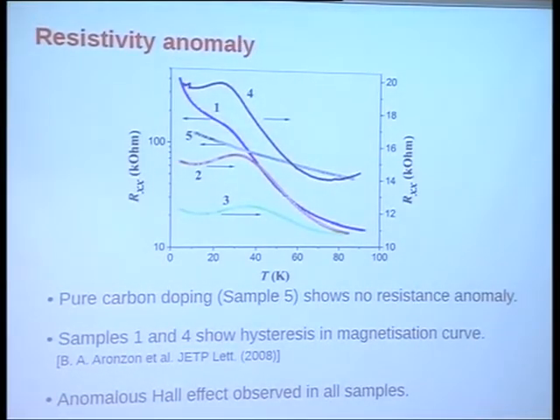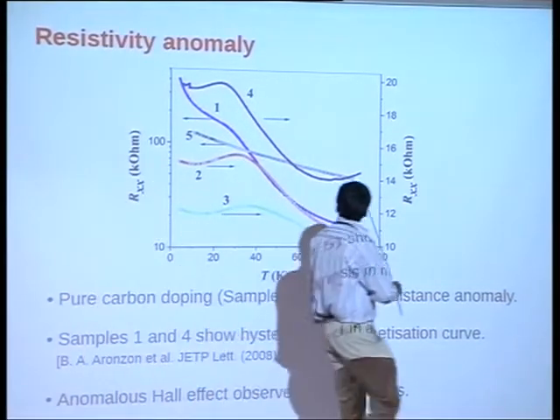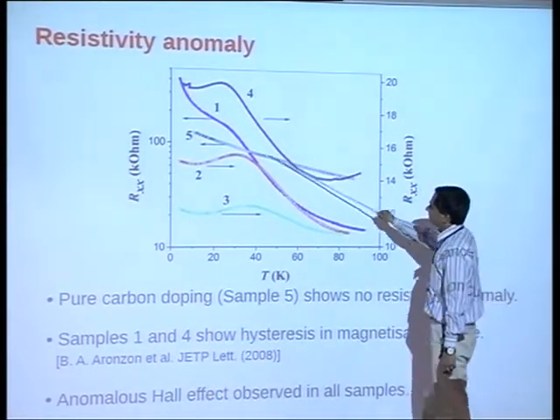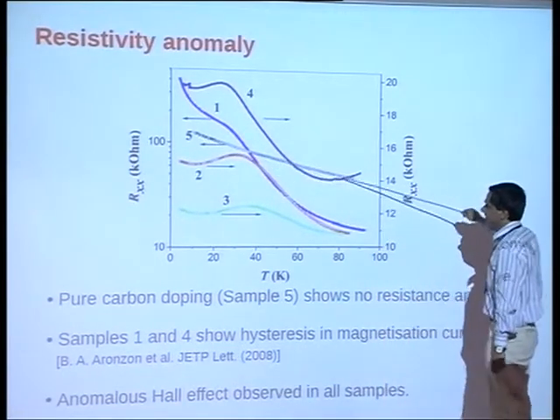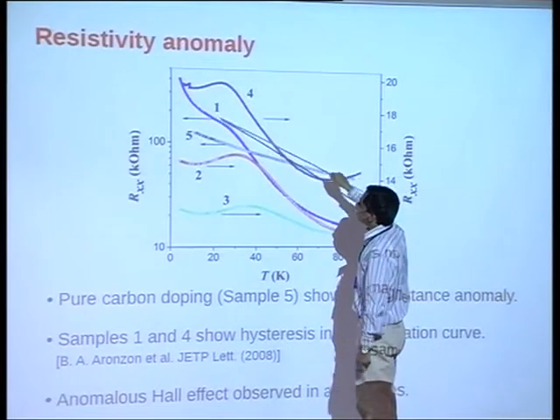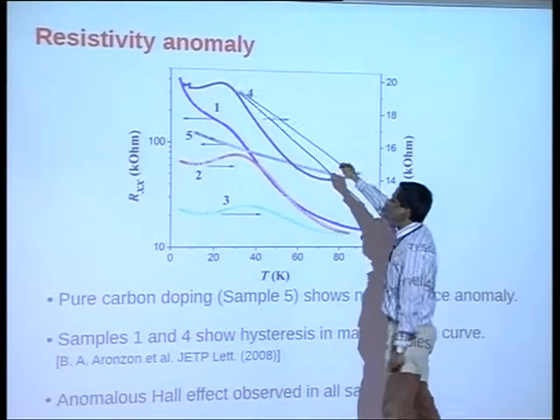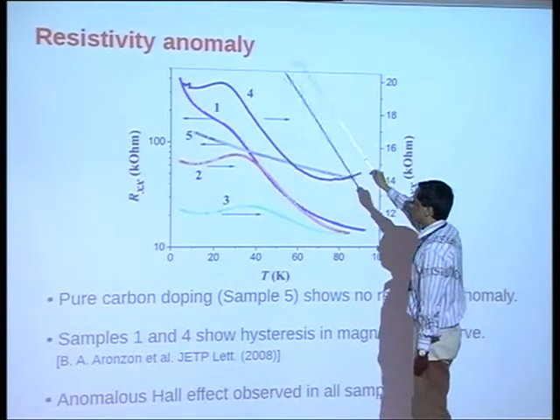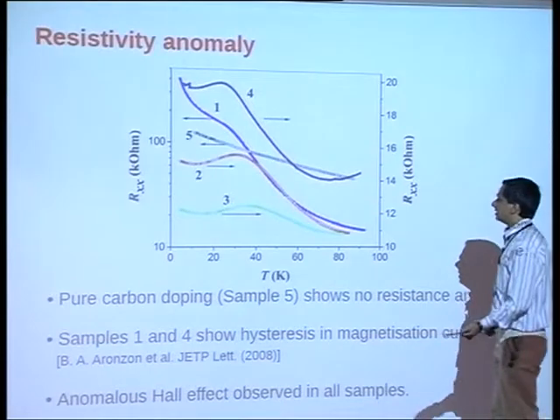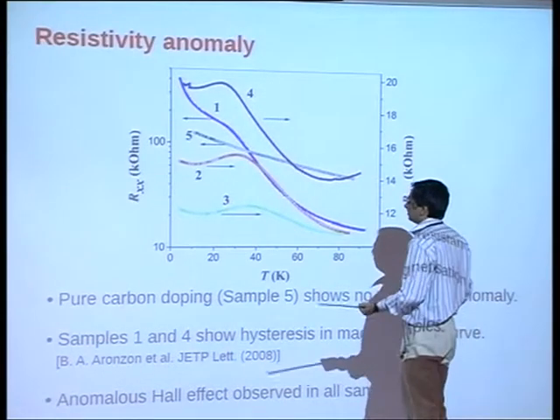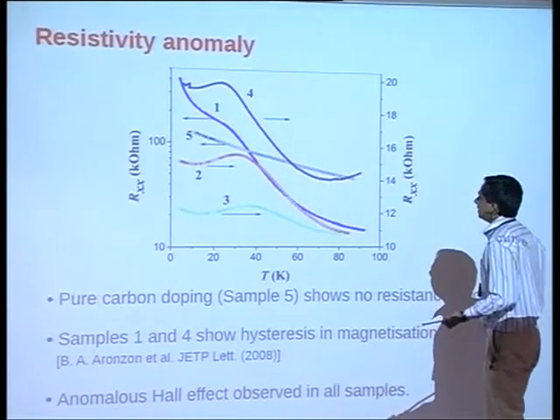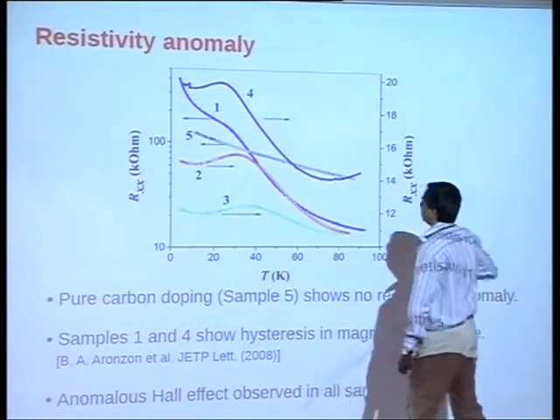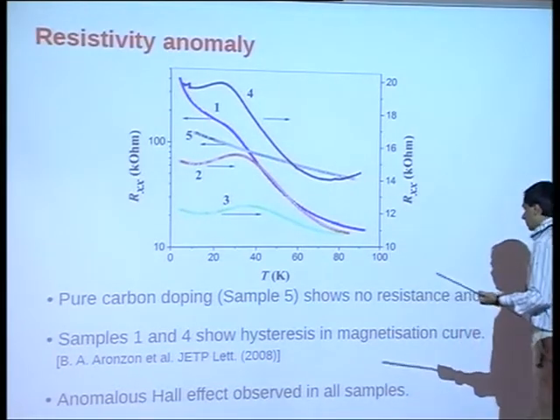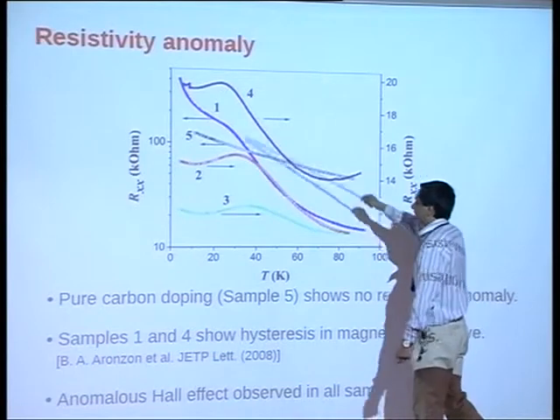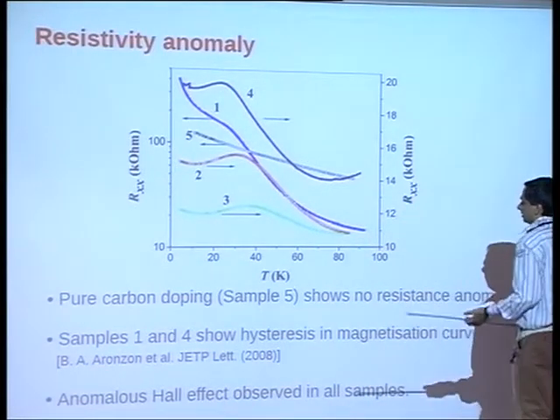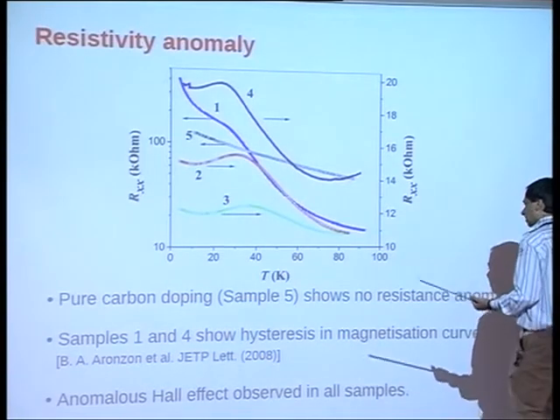Okay, now the resistance. All of them except the purely carbon-doped one, which is shown here for control reasons, show anomalies or shoulders at some characteristic temperature, which is roughly in the same ballpark range, not varying much, even though the carrier densities and the doping density have been varying. There is some change here systematically, but not that strongly. And so we suspect at this point that these are probably due to ferromagnetic correlations.